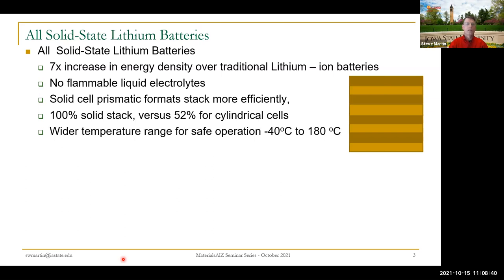However, the other additional advantage above and beyond the energy density advantage, of course, is the temperature range. The Tesla automobile contains cooling systems, temperature monitoring systems to keep those liquid electrolyte-based cells in low temperature and keep them safe. Solids are so much, as all of you know, are so much more forgiving about temperatures. They don't freeze, they're already frozen. Yes, the conductivity has an Arrhenius temperature dependence, but it doesn't catastrophically drop off as the liquid freezes at low temperature. And of course, glass transition temperatures are 300 or 400 degrees Celsius, so there's no problem there. You just run into the melting point of lithium, which is about 180. So 180 degrees Celsius, 300 or so Fahrenheit, a common temperature for an internal combustion engine, makes these solid state cells very flexible for an automobile application.